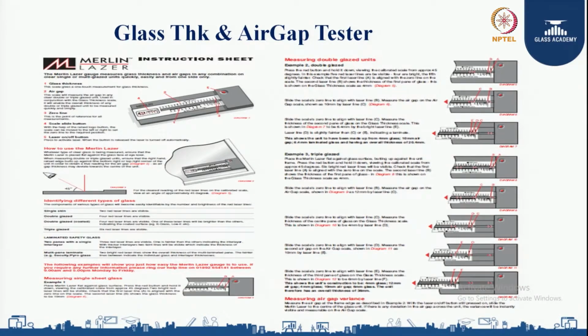Next test is the glass thickness test and air gap test. Since a DGU glass is a combination of a minimum of 2 glasses with an air gap, the air gap tester tells us the thickness of individual panes as well as the air gap between them. Using the Merlin laser air gap tester, we place the equipment on the glass surface to identify these measurements.